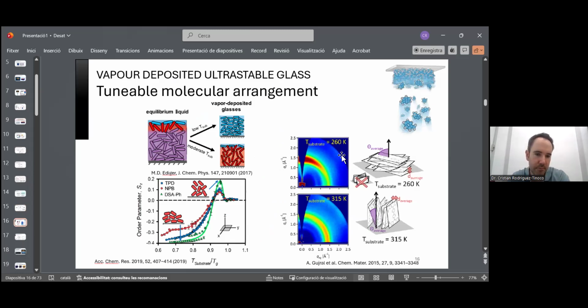Again, these are the experimental points for different materials. This can be measured, as I was saying, with X-ray diffraction. You see here this typical amorphous halo of glasses, no? The distribution of intensity along this halo is not perfectly uniform, as one would expect from a completely isotropic system, but especially in this case, substrate 260, which is low temperature, below 85% of the glass transition temperature of the material, which is TPD, we see here a strong accumulation of intensity, which means that the molecules are, on average, oriented in this way, okay? Parallel to the substrate. Not perfectly parallel, but a significant degree of orientation across this direction.